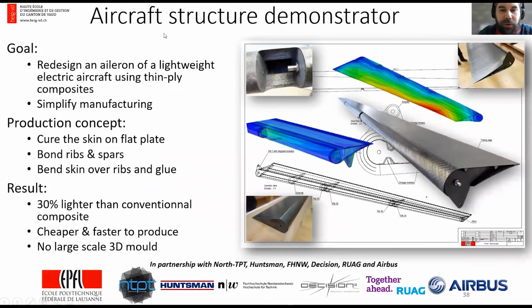We just present one here, which was done in collaboration with RUAG and Airbus and other partners. This is the redesign of a lightweight aileron for an electric aircraft. And the focus here was to save weight and also to be fast and cheap to produce. The main idea was to avoid using a large-scale 3D mold for this aileron. So this aileron is about 2.8 meters long. It has to weigh about 3 kilograms.